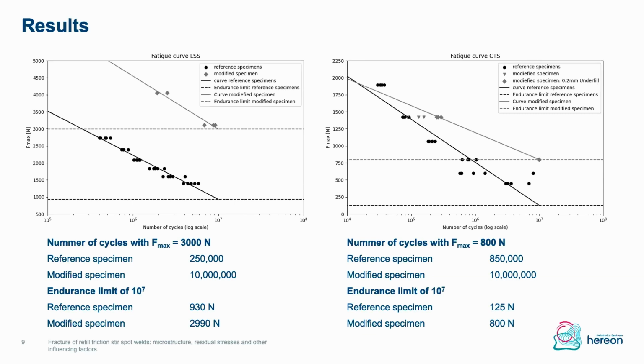And here we saw, especially with lower loads like 800 Newton, we were able to increase the number of cycles from 850,000 up to 10 million, while the endurance limit of the reference specimen was 125 Newton, and with the modified sample it is up to 800 Newton.